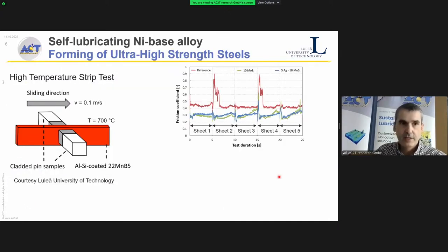We also try a close-to-reality tribometer that is available at Luleå University of Technology in Sweden. In this case, we have a strip test with aluminum-silicon coated ultra high strength steel at 700 degrees, and we always do a single pass, replace the sheet and use a new one. You can see here the results, and you can see that when we use a reference, in this case a nickel-based material without any solid lubricant, friction is high, and also we have these break-ins into the aluminum-silicon coating, with spikes of friction close to 1.